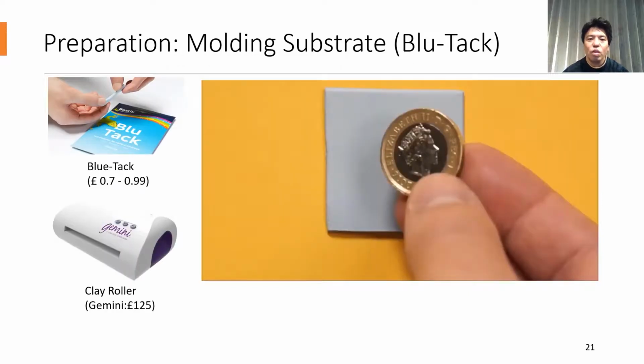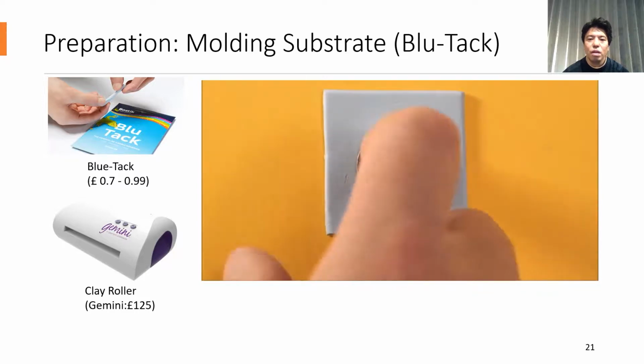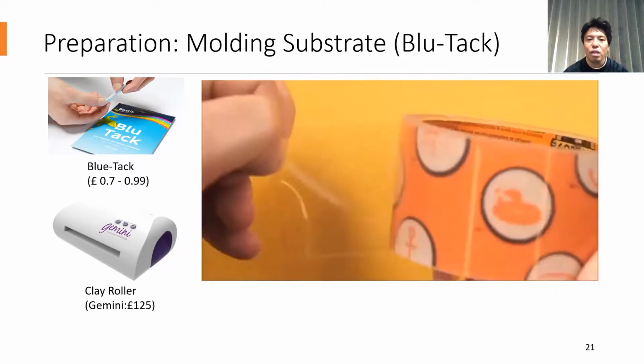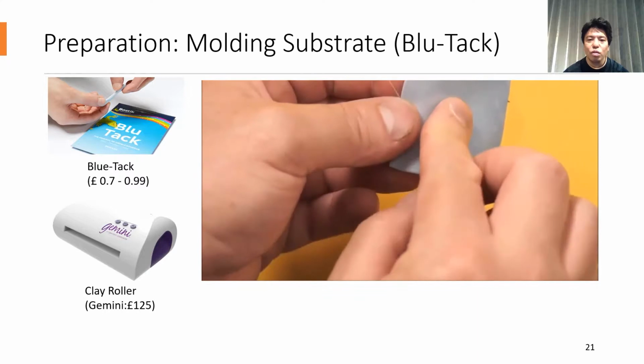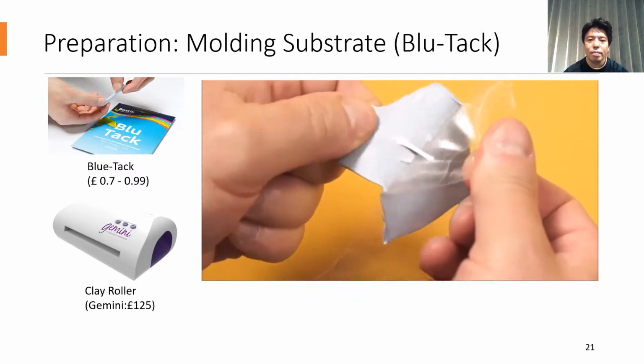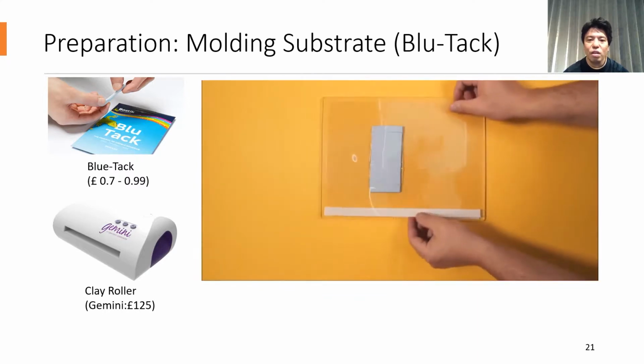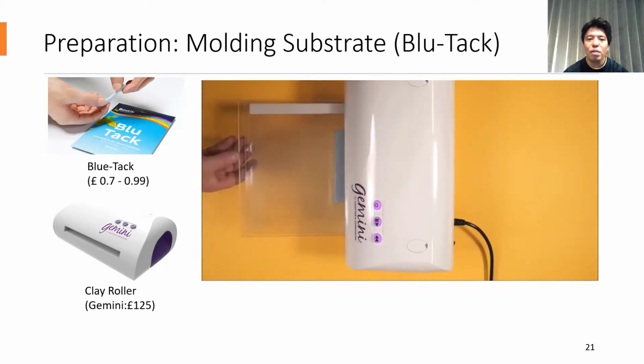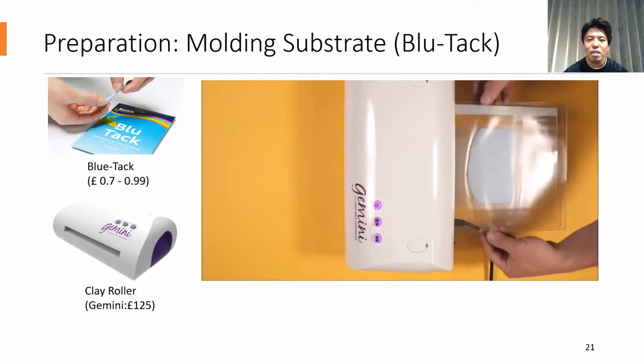As a molding substrate of FlowKit, we use Blu-Tack, which is a commonly available pressure-sensitive adhesive. Blu-Tack works like clay to imprint fine texture and is very sticky to tape. We wet Blu-Tack to reduce adhesiveness and place it between seams, then use a clay roller machine to make an even surface with specific thickness.